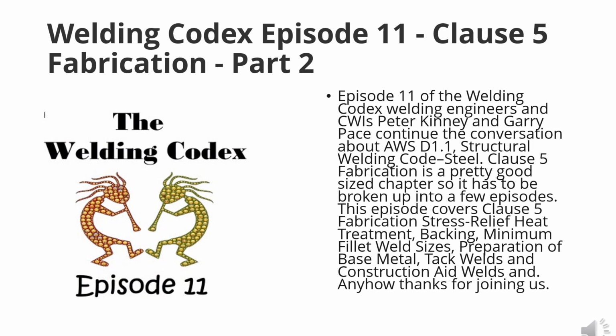Oh, and another one that we kind of glossed over, but gets back to acting like a grown-up and doing this stuff correctly. Tack welds incorporated into final welds shall be made with electrodes meeting the requirements of the final welds. These welds shall be cleaned prior to incorporation. So if you're doing a weld on a 90 KSI material, you can't be using 60-10 and then incorporating those tack welds into your final weld, or 70-18 or whatever. It has to meet the requirements of the final weld.